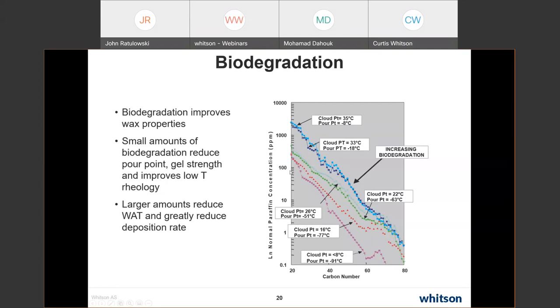So these were made with cold finger, so they actually are showing the real wax deposit for the cloud point measurement. Because we know what will happen is if we get into these severely biodegraded systems where all the normal paraffins are gone, it's going to be hard to see anything on DSC or CPM. So, if I have a lot of biodegradation, I'm usually going to be in an area where wax is not really an issue, although the biodegradation does negatively impact oil quality.